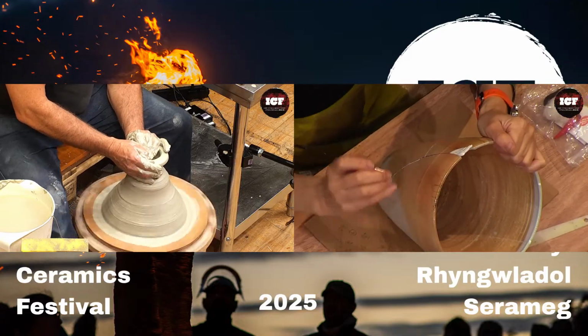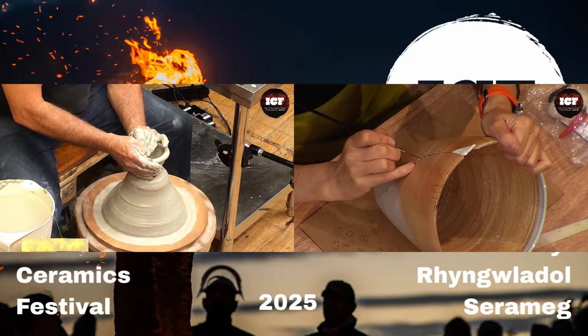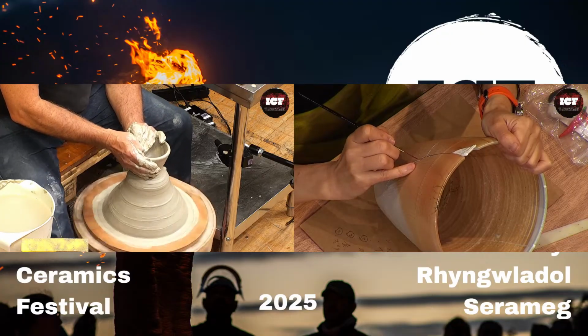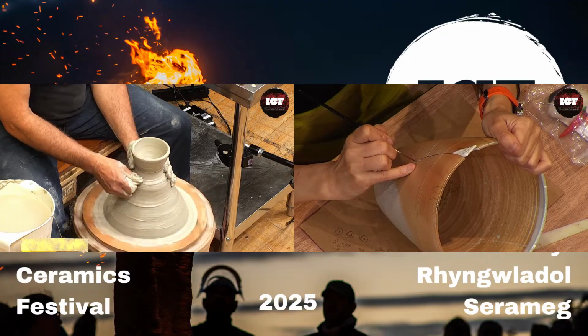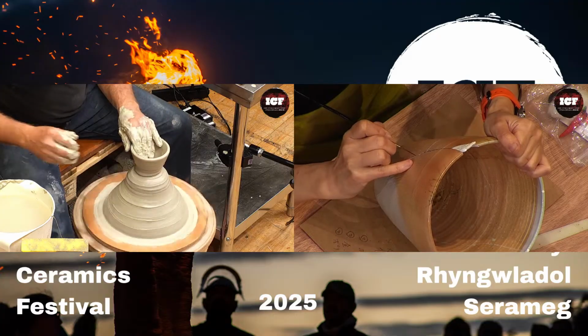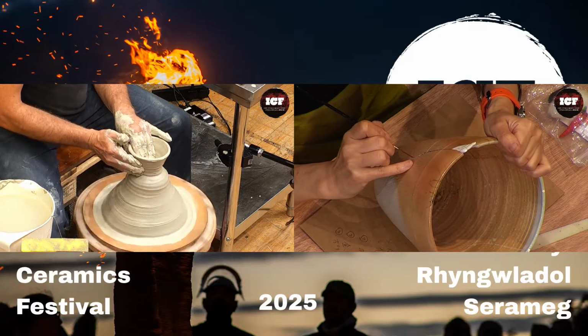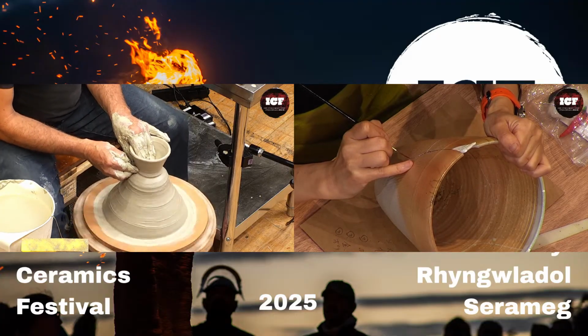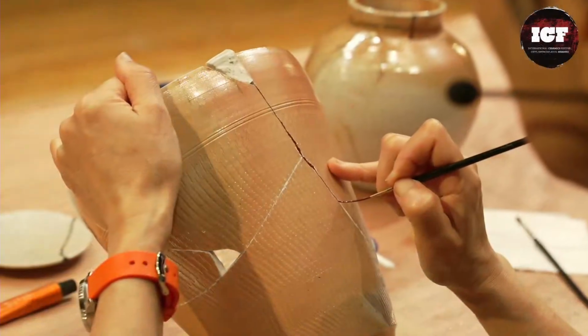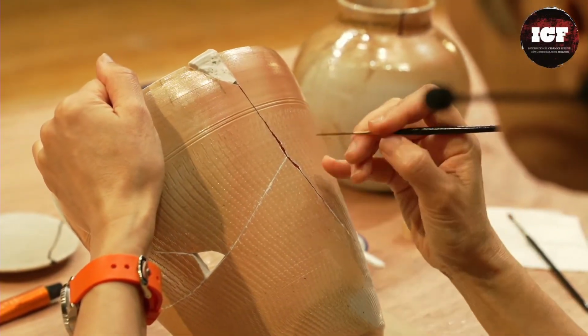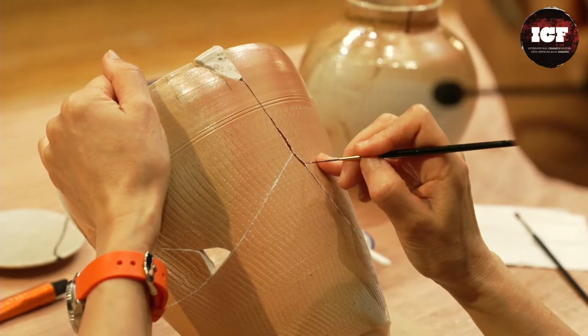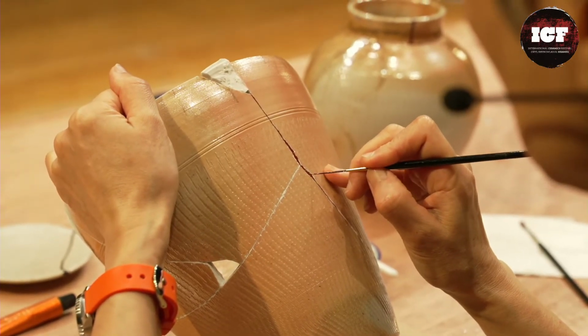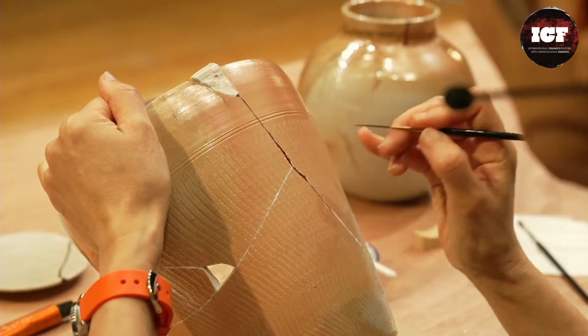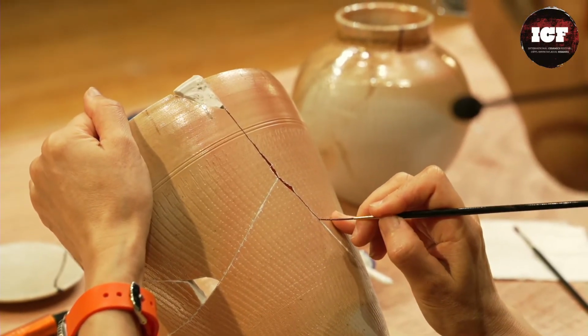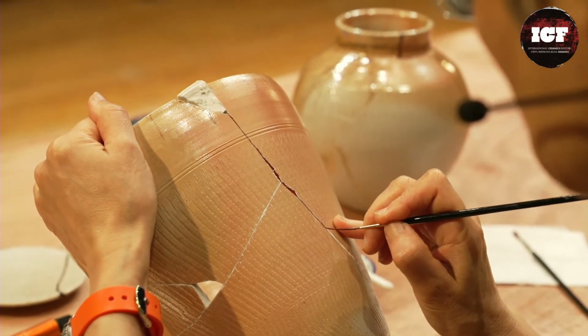With the cristobalite, if the cristobalite forms, then no matter how slowly you cool it, in fact, the slower you cool it, the more crystals form, so that you end up with a stress between the two different sorts of silica against each other, shrinking at different times and different rates, and you'll get dunting. So no matter how slow you cool it, the slower you cool it, the worse it is. And you pull out your pots and the bottom half just falls off because of stress cracks.